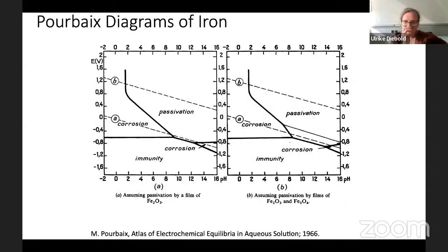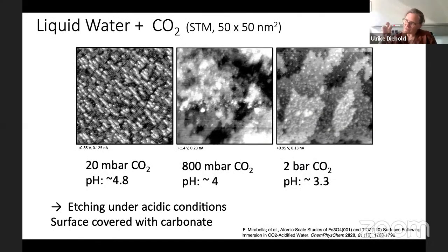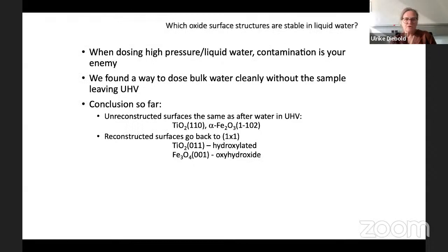So maybe one more thing we try. People ask, can you put in an electrolyte? Not yet, we're working on this. One thing we can do a little bit is change the pH of this very clean water drop. So this is the Pourbaix diagram of iron with pH. I don't measure the pH, but it's pure water, so I assume I have this electrochemical potential and pH 7, somewhere here. But we can change the pH a little bit towards more acidic, and we do that by opening the valve and putting in some CO2 when we have this water drop. If we saturate that at different pressures, we can go to relatively low pH values, and then look at what the surface did. So we can even etch under acidic conditions, and what we found is, of course, that the surface is covered with carbonate. Okay, so that's where we are at this point.